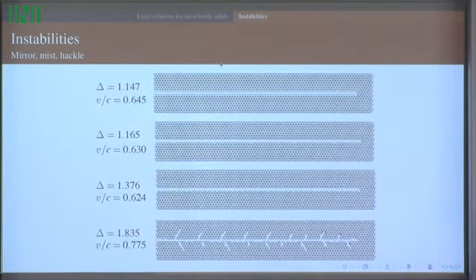Now, in the context of these models, this is actually something which you can try to calculate, and the way you can try to calculate it is as follows. I carried out calculations in the triangular strip, and one of the things you can do is to compute the stretch of horizontal bonds above the crack line. And just as it paid to be very attentive to precisely when the ones along the crack line broke, now you can start being attentive to whether any of the bonds above the crack line should break, or whether they're always kept below their breaking point.